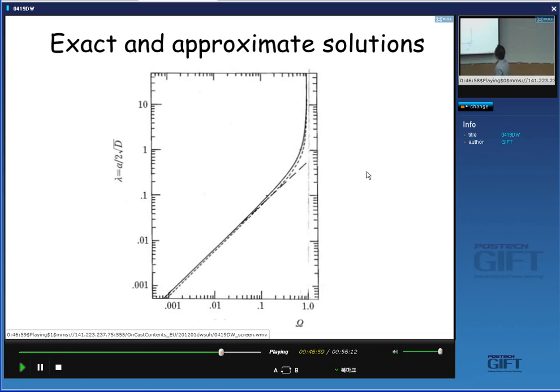Of course, this is for the linear planar growth. But when we move to a cylindrical or spherical shape of the product phase, then the linear gradient approximation may not be a good choice. So you have to remember that the applicability of those kinds of simplified approximations strongly depends on the shape of the product phase.